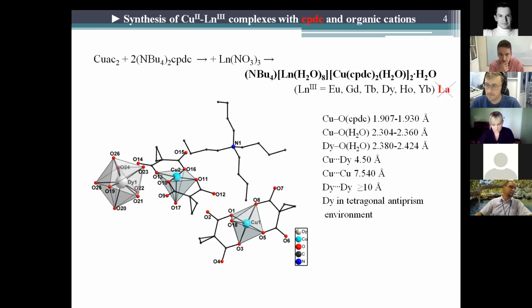It was found that the reaction between copper acetate and the tetrabutylammonium salt of cyclopropane dicarboxylic acid in the presence of lanthanide nitrate gave an ionic lanthanide copper complex. Two bis(cpdc)copper fragments crystallized with lanthanide octa-aqua cation and tetrabutylammonium cation as counter ions. Copper is situated in a tetragonal pyramidal environment with an axial water molecule. Distances between all the metal centers are more than 4 angstroms, and metal atoms are not connected by bridging groups.